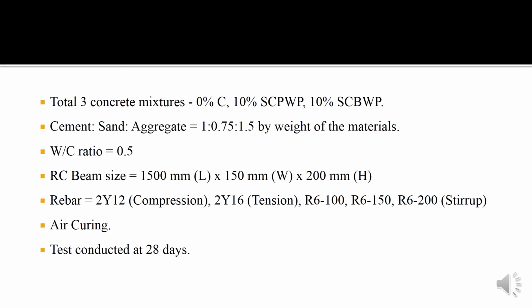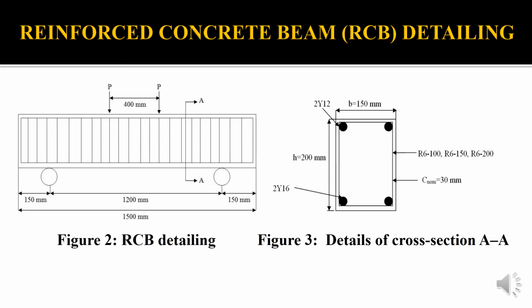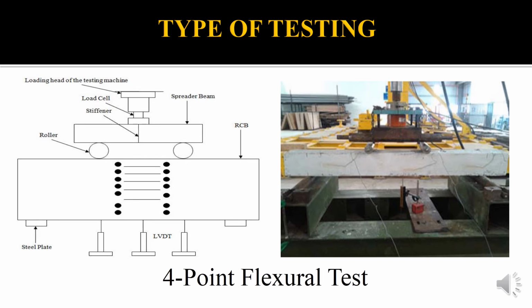The reinforced concrete beam size is 1500 mm length times 150 mm width times 200 mm height. The rebars used are 2Y12 for compression, 2Y16 for tension, and three types of stirrup spacing, which are R6-100, R6-150, and R6-200. The test is conducted at 28 days of air curing. Figure 2 shows the reinforced concrete beam detailing, while Figure 3 shows the details of the cross-section. The test conducted was a 4-point flexural test.